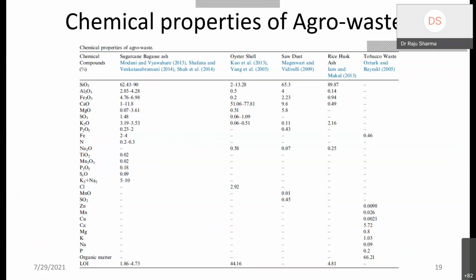So if you see the sugarcane bagasse, it has 62.43 to 90% of silica, and alumina of 2 to 4%, and Fe2O3 of 4.76 to 6.98%. And then calcium also 1 to 11%. So this range is very high.